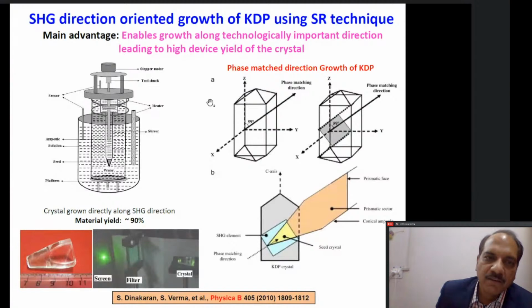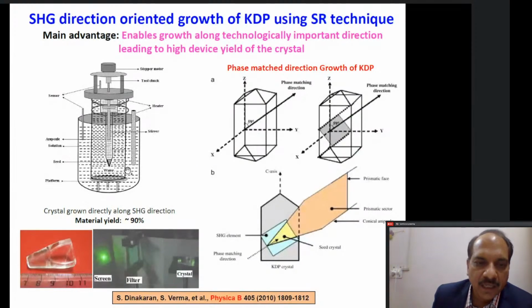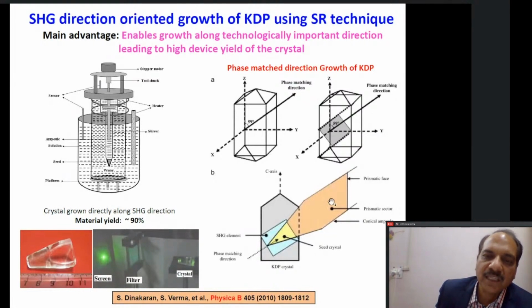So we made a setup. In fact, the student Jerome Das, Dr. Dinakaran, made this setup in my lab, and I told him that instead of growing it directly in the natural morphology, you should grow it in this way. So he followed that instruction. He made a seed crystal in a conical form, where the axis of the cone was the phase matching direction. This cone was put at the bottom of this ampoule, and then we allowed this crystal to grow. This was the final crystal, grown after about 10 days.